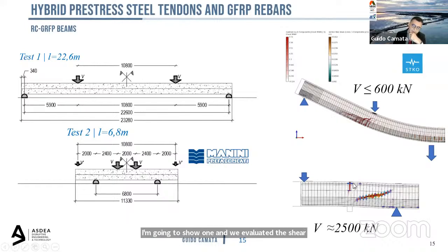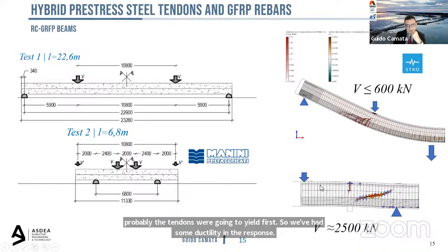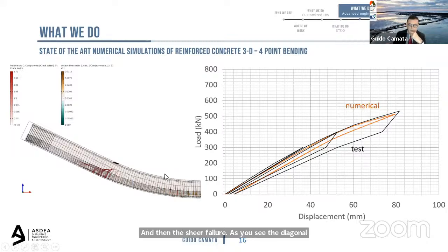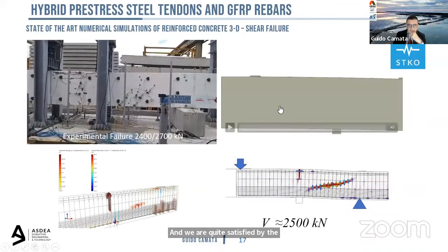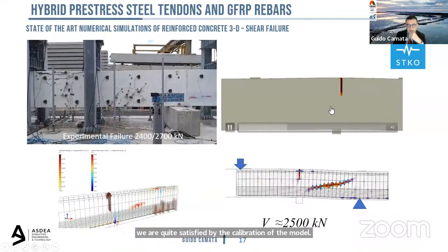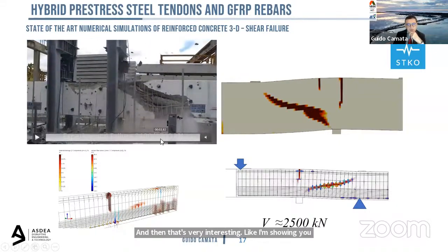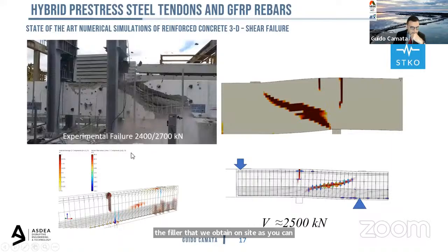And we also found out that probably the tendons were going to yield first. So we would have some ductility in the response, and then the shear failure, as you see, the diagonal shear failure. That was a response of the test in flexure. You see the numerical reproduced very, very well the test. And we are quite satisfied by the calibration of the model. And then that's very interesting, like I'm showing you the predicted failure and then the failure that we obtained on site. As you can see, the model reproduced perfectly the test.